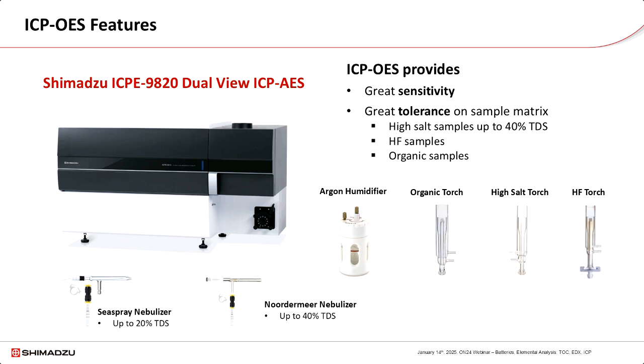Compared to other elemental techniques, ICP-OES provides great sensitivity. It can measure a lot of elements down to ppb detection limit. It has great tolerance on sample matrices. For example, it can measure high salt samples up to 40% total dissolved solids. It can handle samples with hydrofluoric acid, which is very nasty and can attack glass. It can also be used to analyze organic samples directly.